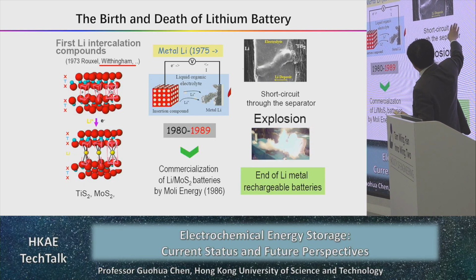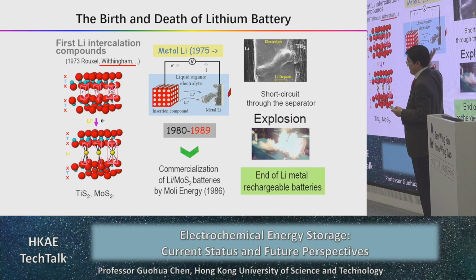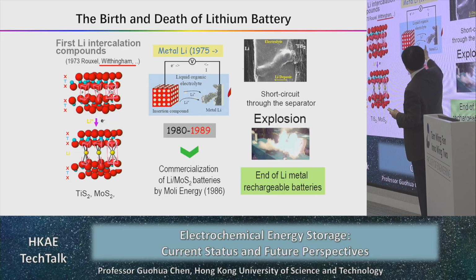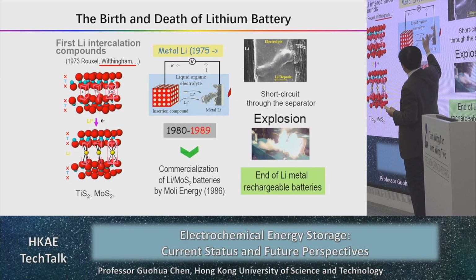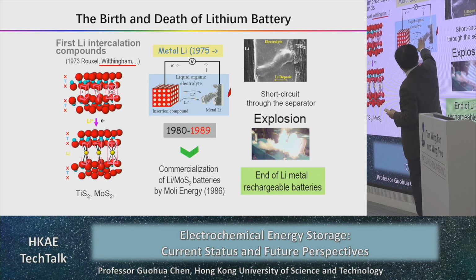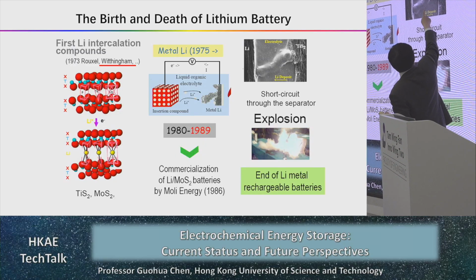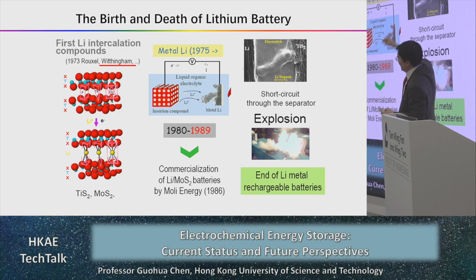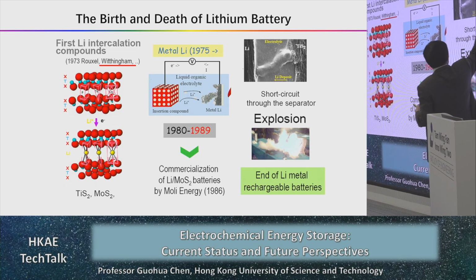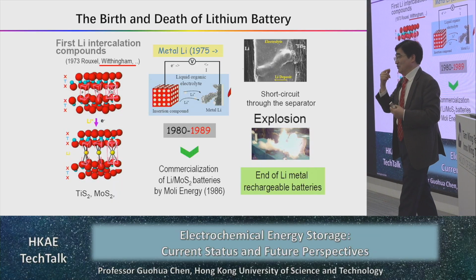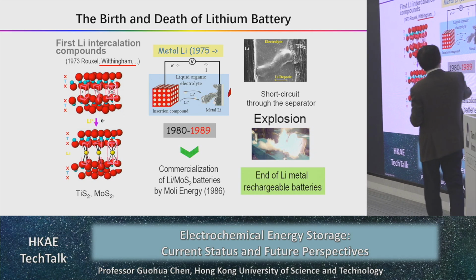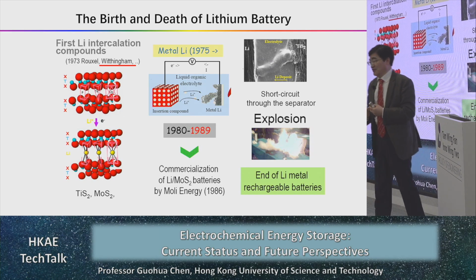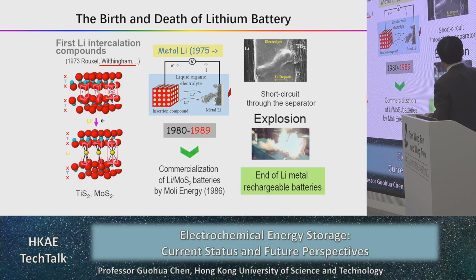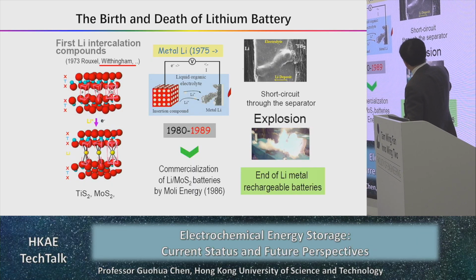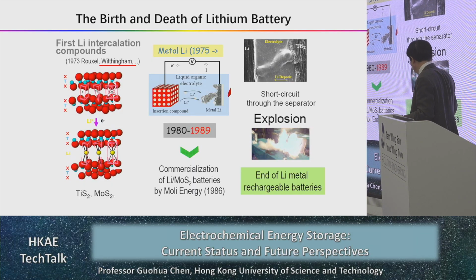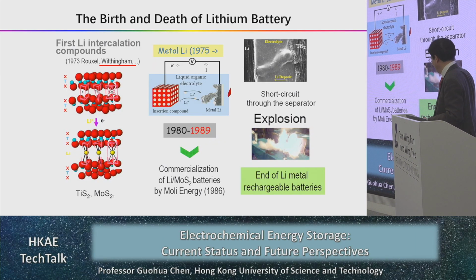And the problem is, after maybe 10s, 20s of cycles, depends on how you use it, the lithium could deposit and strip, deposit, strip, but deposition of the lithium could have this dendrite formation. If this dendrite formation is so big and so strong, it can penetrate through the separator and contact the cathode. Anode cathode contact, then you get short circuit. Short circuit means a large current and thermal runaway, explosion. And because of this safety issue, this is the end of the lithium metal rechargeable battery.